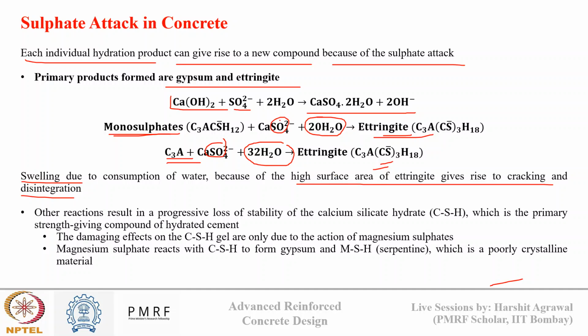So this is the reason how sulfate attack is causing problems in concrete, due to swelling of the hydration product. Here you see sulfate ions reacting with monosulfates and calcium aluminates to form ettringite, which is consuming a lot of water and forming a hydration product with high surface area, and accommodating this high surface area product inside concrete can give rise to cracking and disintegration.